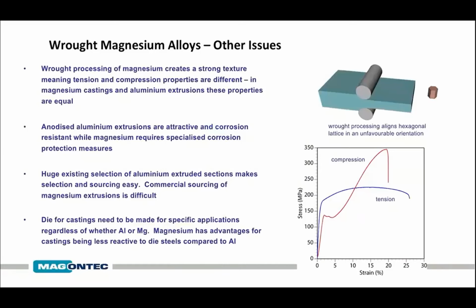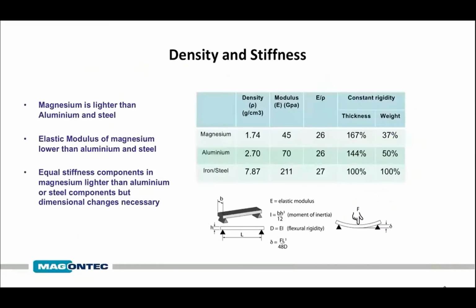And magnesium has advantage for castings over aluminium, being much less reactive with the die. The big factor for magnesium is the lower density, used for weight reduction. As you can see here, the relative density of magnesium is 2/3 that of aluminium, a 1/4 of that of steel.